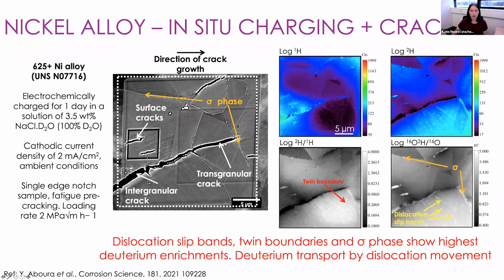Here we can see we have a crack running through this sample surface, an intergranular crack to a transgranular crack. We also get some surface cracking due to the charging conditions used here. And in this particular alloy, we can see we have sigma phase here on the grain boundary, which was of interest for us as well. Now we can see we have deuterium localizing to twin boundaries, deuterium localizing to dislocation slip bands, and deuterium localized to sigma phase as well. All of these regions show the highest deuterium enrichment. So what we've got now is deuterium transported by dislocation movement. Again, the relationship between dislocation movement and deuterium once again.